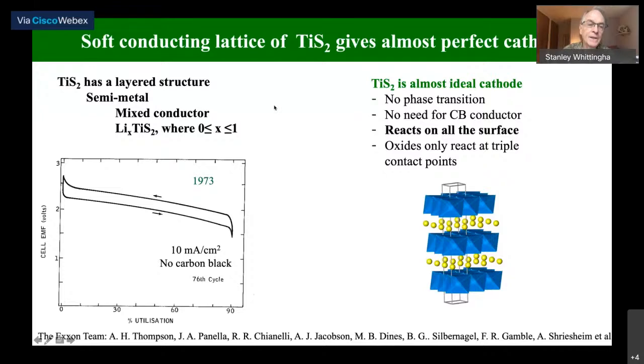The big advantage of titanium disulfide, it has essentially metallic conductivity. So you don't have to mix carbon or other conductive materials with it, which means it can react all over its surface, not just where the carbon, the TiS2 and the electrolyte meet. So we can get very high current densities. I show you here, this is 10 milliamps per square centimeter, higher than any of today's batteries work.